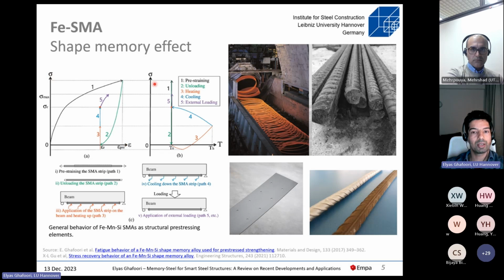So here we have stress-strain and stress-temperature behavior. This curve shows the pre-straining process and unloading. So we pre-strain, let's say, a strip, we unload that, right? And then we apply that to a civil structure. It could be a concrete beam, a steel beam, timber beam, and we could bond the shape memory alloy to a steel beam, or we could actually use rivets or bolts to connect them, and then we heat them